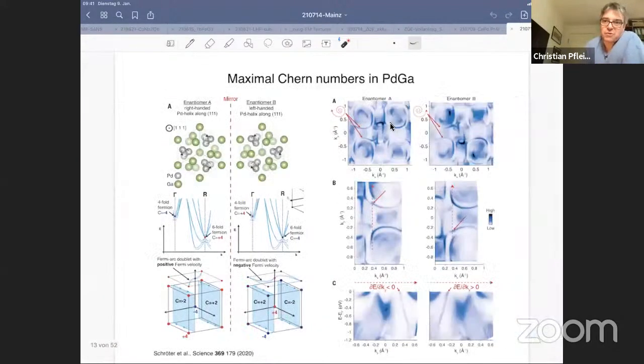on. Of course, since the spin-orbit coupling in cobalt silicon is very weak, there was last year a very nice paper reporting ARPES in palladium gallium, where the spin-orbit coupling is much, much stronger. And they, on top of it, showed that since the crystal structure is chiral, right, if you have the other enantiomer, the chirality of these crossings would change. Right? So that was part of the story that basically could now better resolve